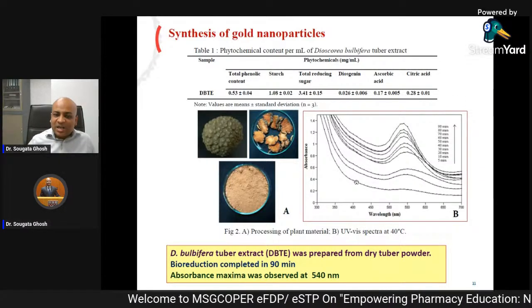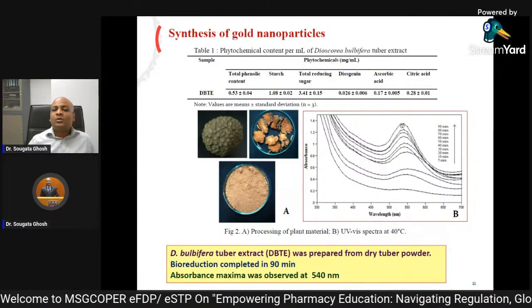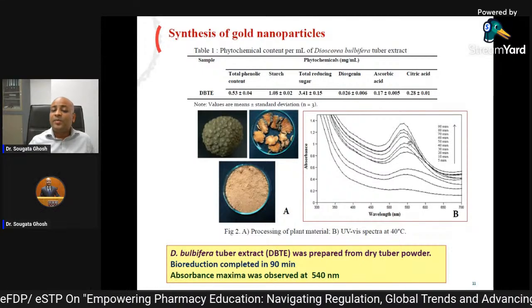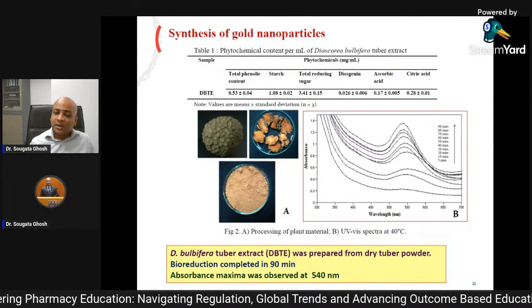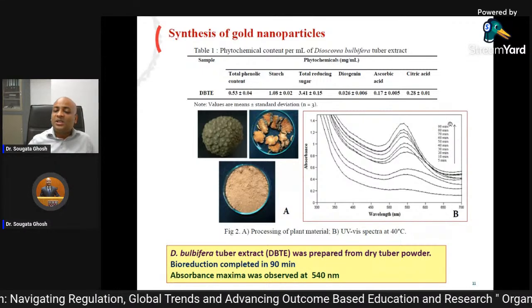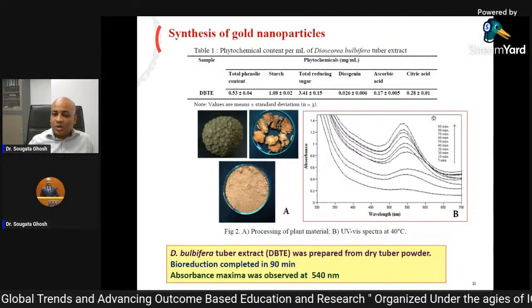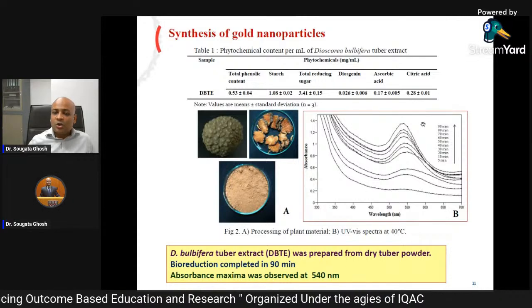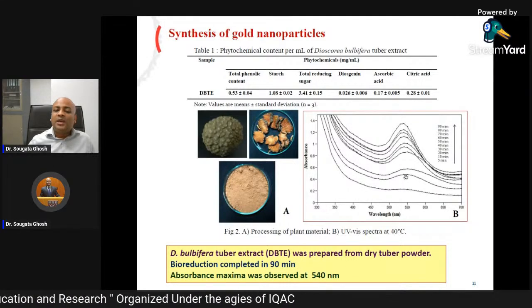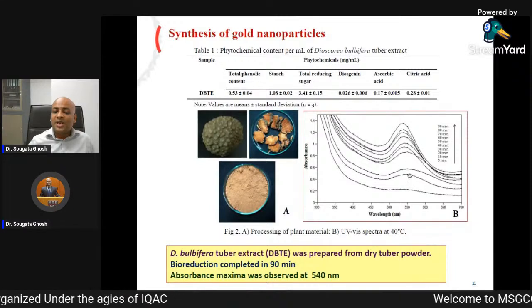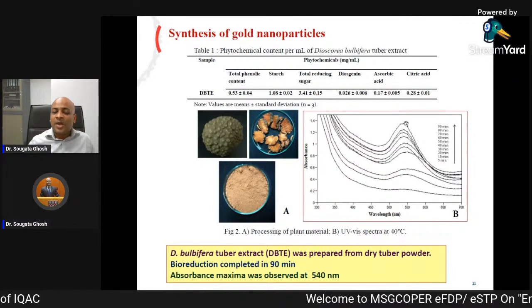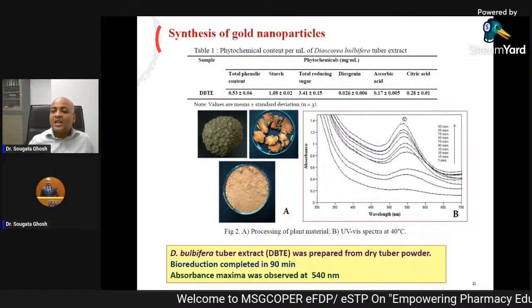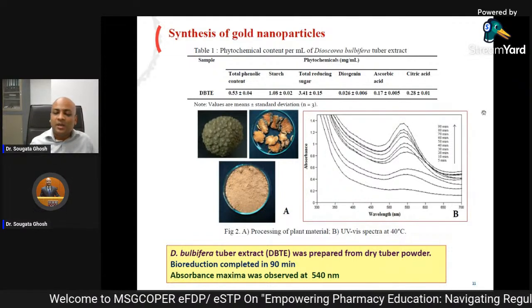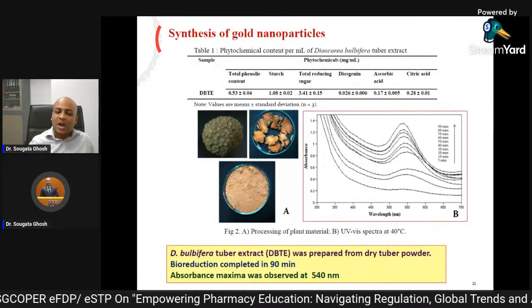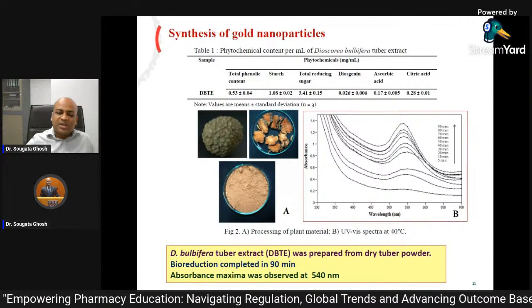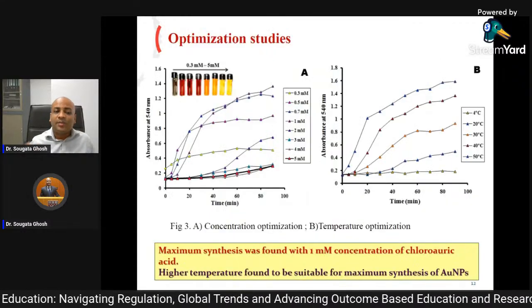So why can't we use that for synthesis of nanoparticles? That's why we started reacting with gold chloride solution, and it was one of the fastest methods of synthesis. People take 5 hours, 6 hours, 1 day, but here the gold nanoparticle was synthesized within 90 minutes. So this is the UV visible spectra. It showed a peak that developed continuously from 5 minutes, 10 minutes, 20 minutes, till 90 minutes at 540 nanometer. And this 540 nanometer is the signature peak of gold nanoparticle. So this was a confirmation that gold nanoparticle might be synthesized within 90 minutes.